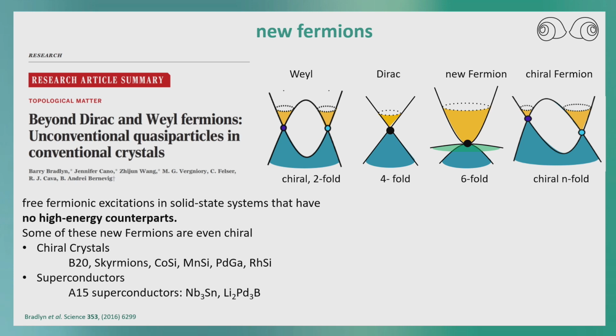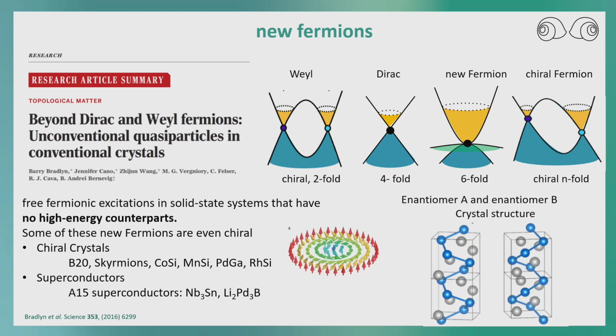And even if you have a chiral crystal, so you have no mirror plane, you can have these Weyl points at different energies. So this was a theoretical prediction, which also got a lot of attention, but at this time we were aware that there are very nice chiral crystals, because I was also working on skyrmions with Stuart, and there's this famous chiral crystal structure, the B20 structure, where you see very nice topological features in magnetism in real space.